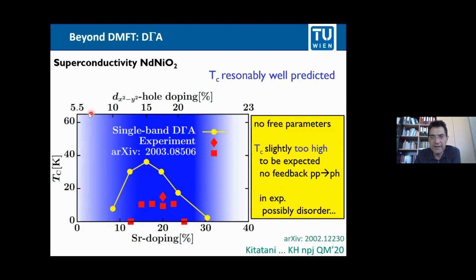And let me mention here the importance of this blue background also. That is the regime where you can trust the one-band Hubbard model. For small dopings, at least for the nickel compound, you should expect the gamma pocket. For larger dopings, you should expect instead z-squared orbitals to play a role. Of course, here this transition we can't precisely predict. Yeah, there is some uncertainty in the method. It can be a little bit more here or a little bit more there. But we know for somewhat larger dopings, these z-squared orbitals come into the game, and for smaller dopings, also the gamma pocket may play a role.